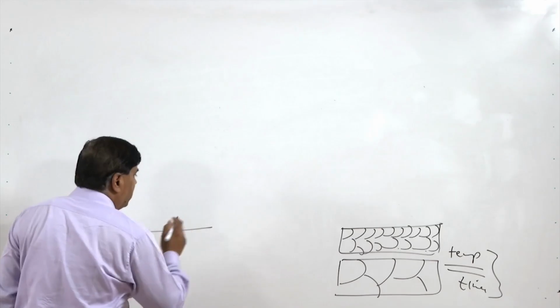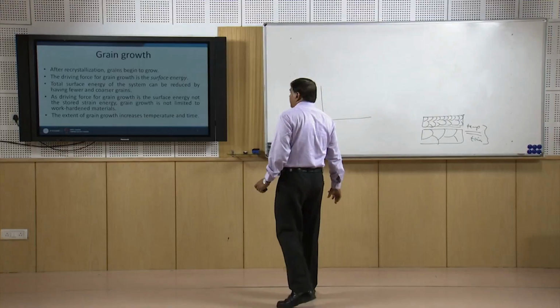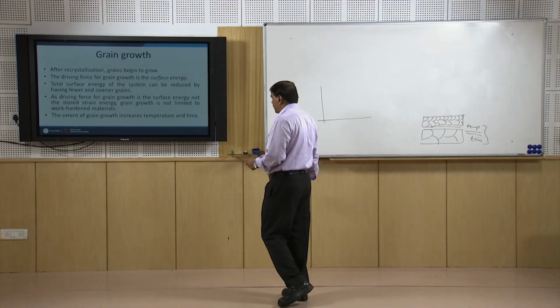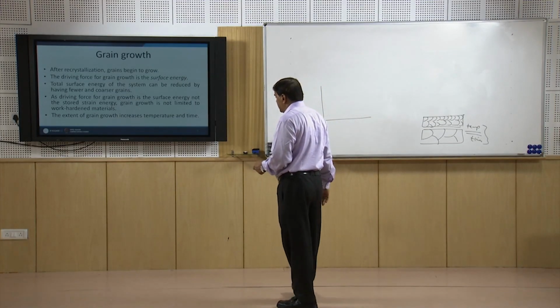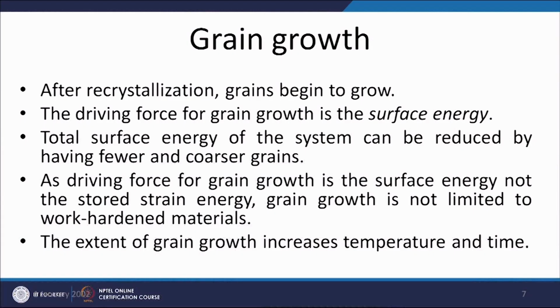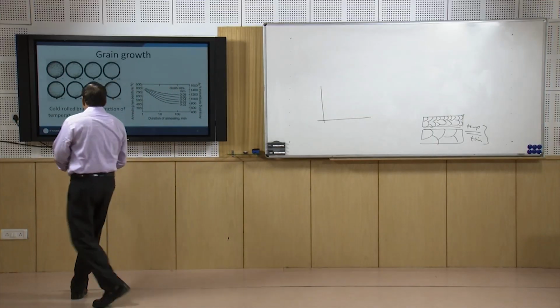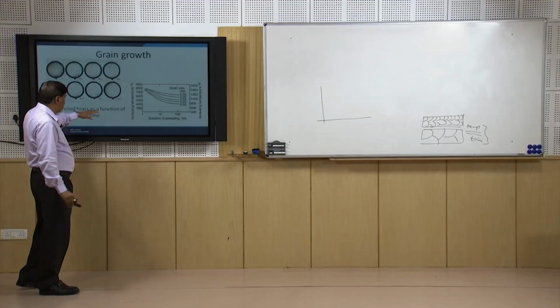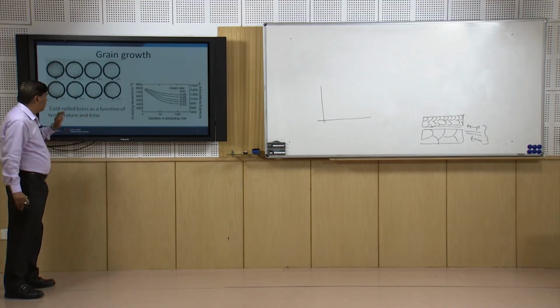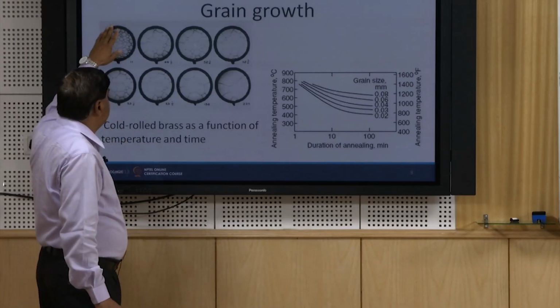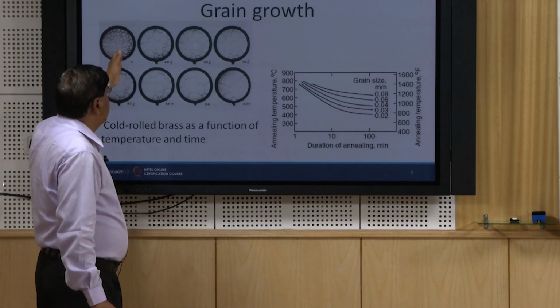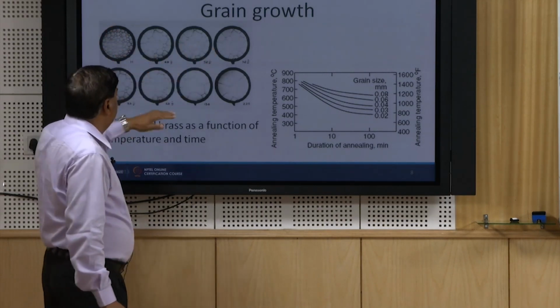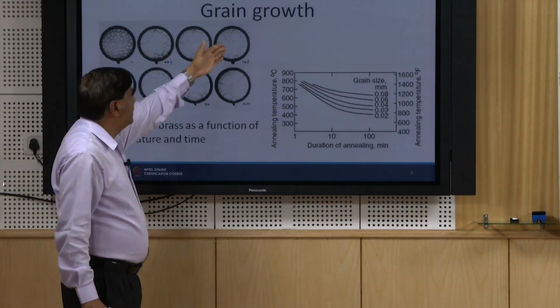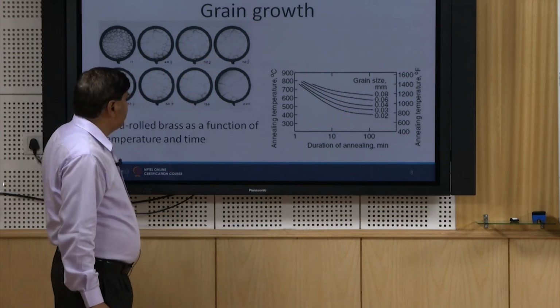Now we will see the way by which grain growth is affected. The driving force for grain growth is the surface energy, not the strain energy. So, grain growth is not limited to work hardened metal systems, but is applicable in all cases. Say for a cold drawn metal system, how is the grain size affected as a function of time and temperature? This is what we can see: work hardened metal systems have very fine grains, and as the exposure keeps increasing in terms of time, you will see a continuous increase in the grain size.